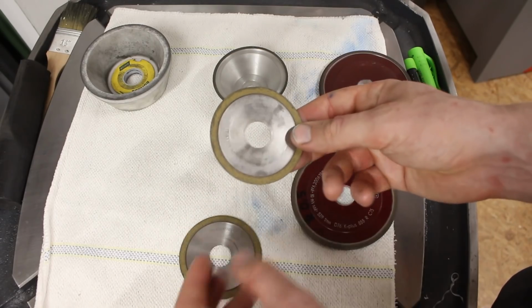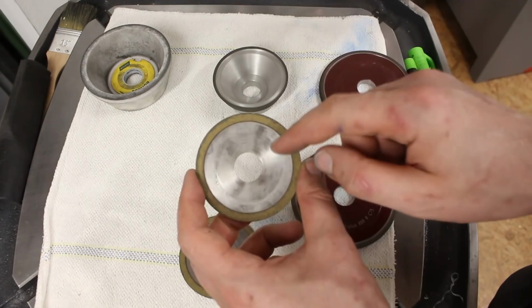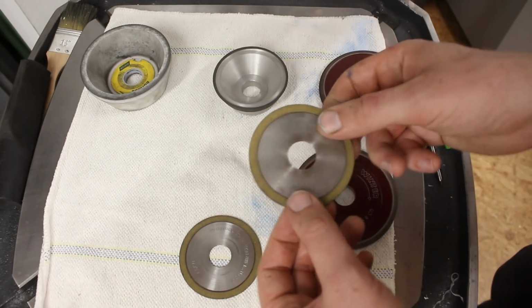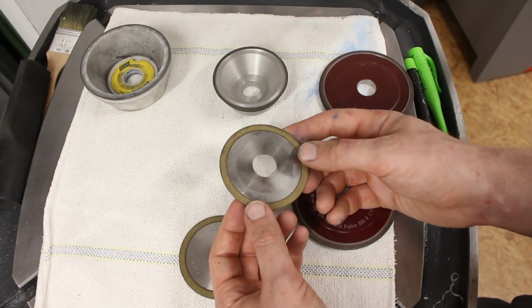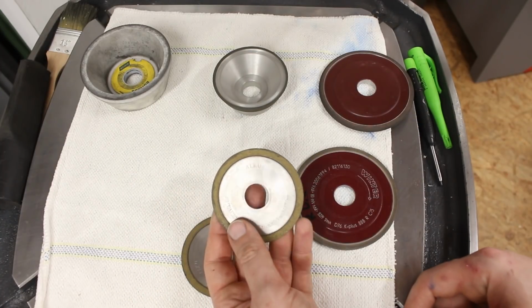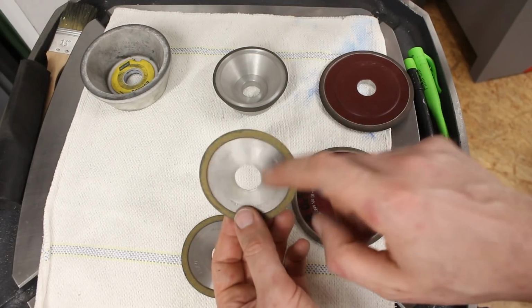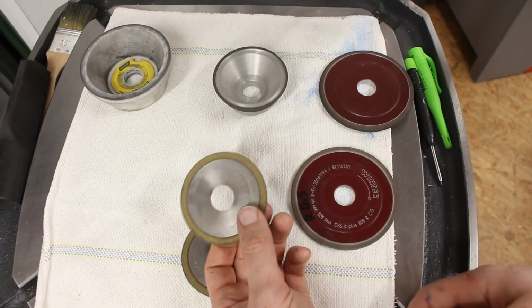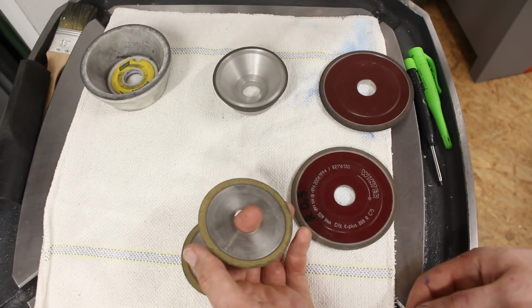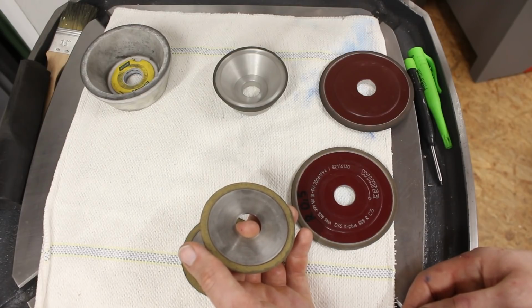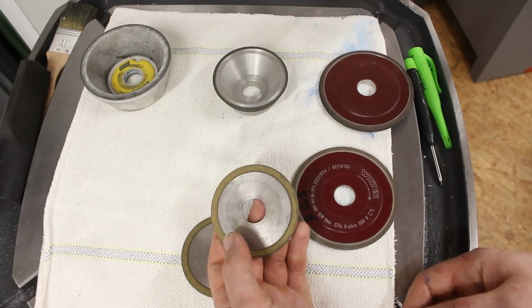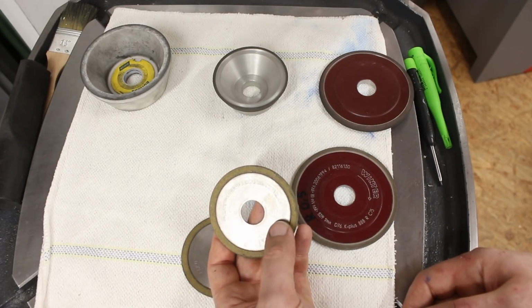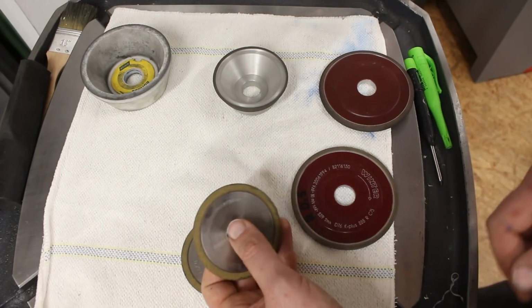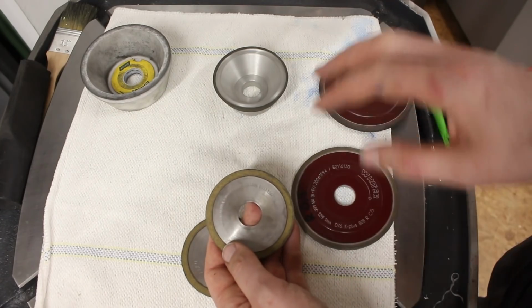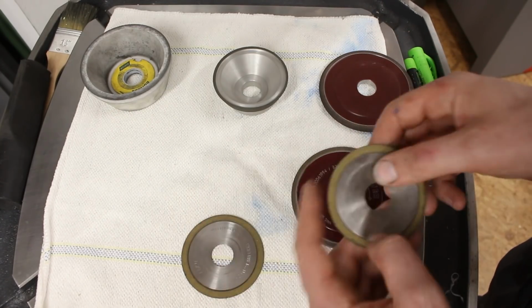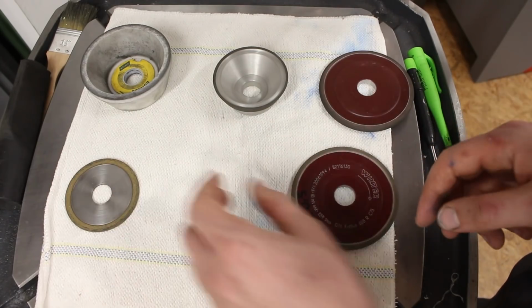Diamond cutoff wheels. These are resin bound diamond cutoff wheels. They cut fairly nice, fairly fast. You need those to cut carbide. If you want to shorten an end mill or make a specialized cutter, you need these to cut the carbide. Yeah, you can kind of score carbide with a small Dremel diamond wheel and snap it off, but usually if you do that, you create micro fractures in the carbide and hairline cracks through the entire piece of carbide, and it's a mess. Very bad results doing that.